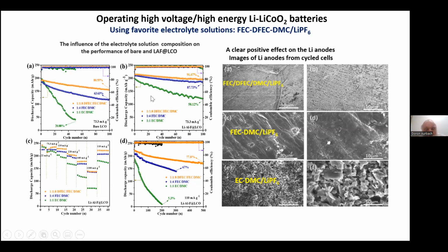But we found that if we go to 4.6 volts, and now we do two things. We use a coating. We use an aluminum fluoride lithium coating. We can use other active metals here, but take a compound comprising lithium, aluminum, and fluoride. It's an aluminum fluoride material. So this coating stabilizes the LCO, and then we use our favorite electrolyte solution which contains the DFEC and FEC, the two fluorinated co-solvents together with DMC. And now we see very nice stabilization, going from bare LCO to the coated material with the nice stabilization, and then by